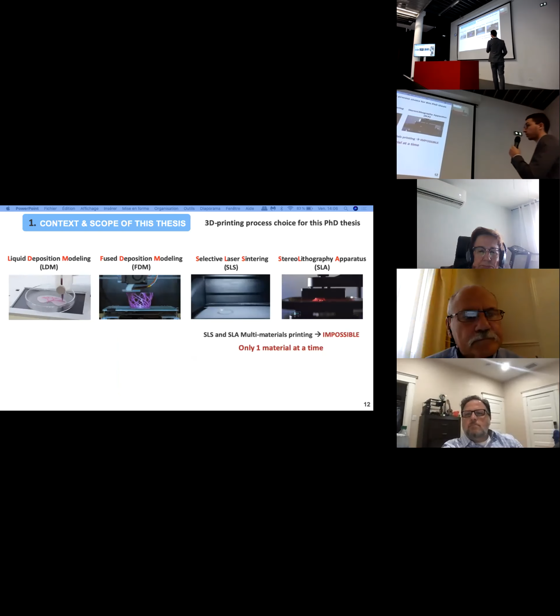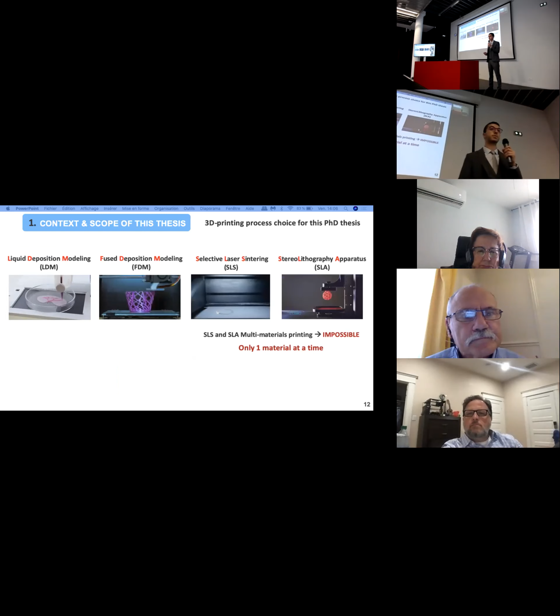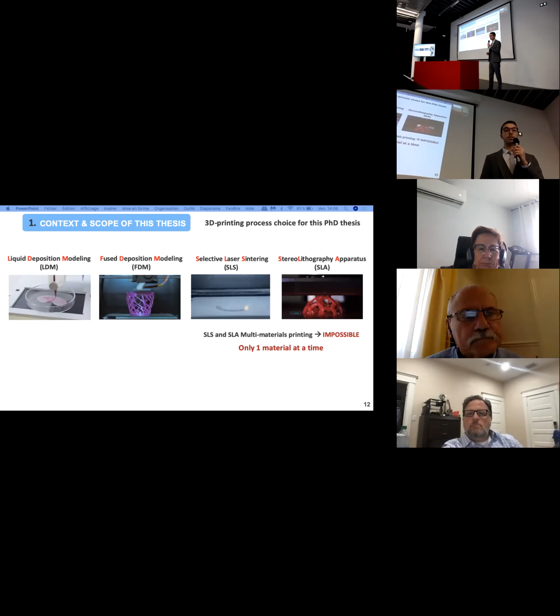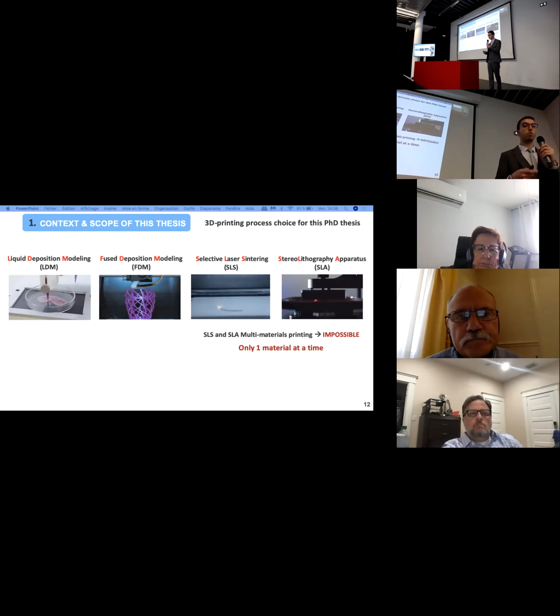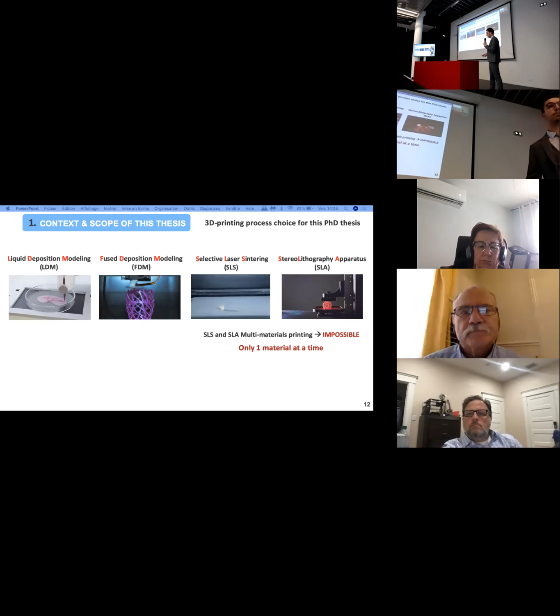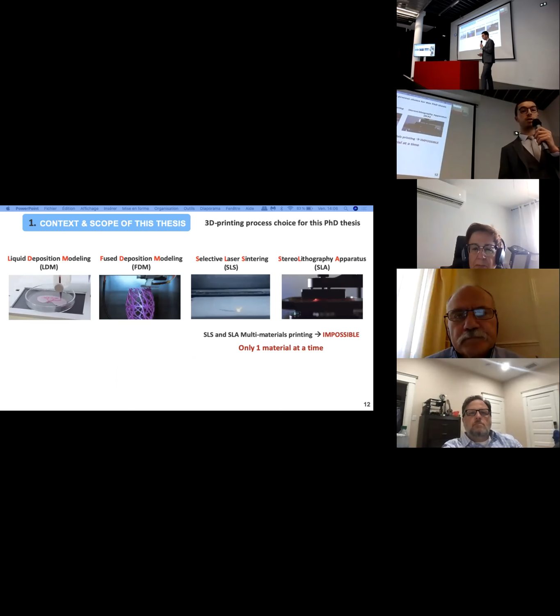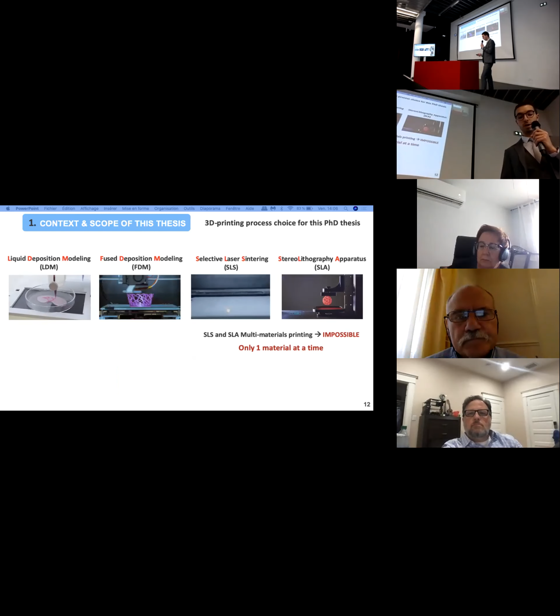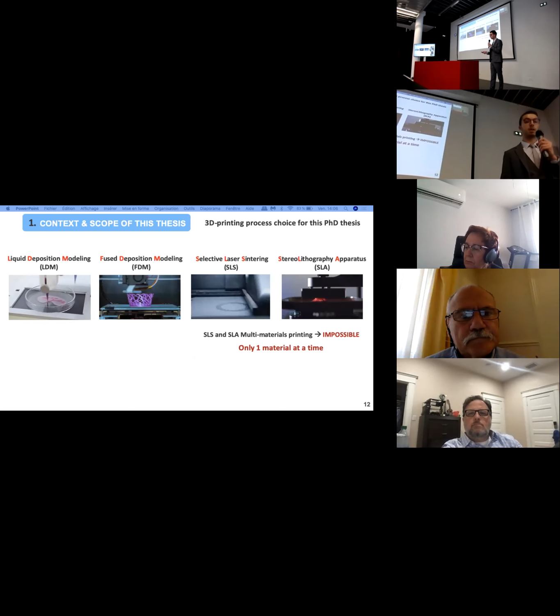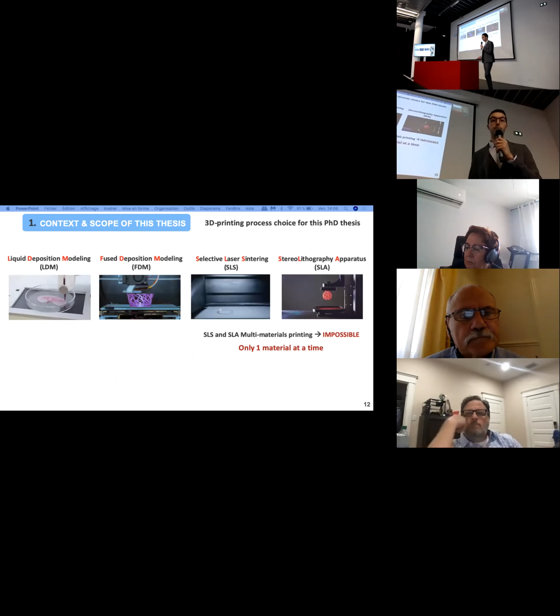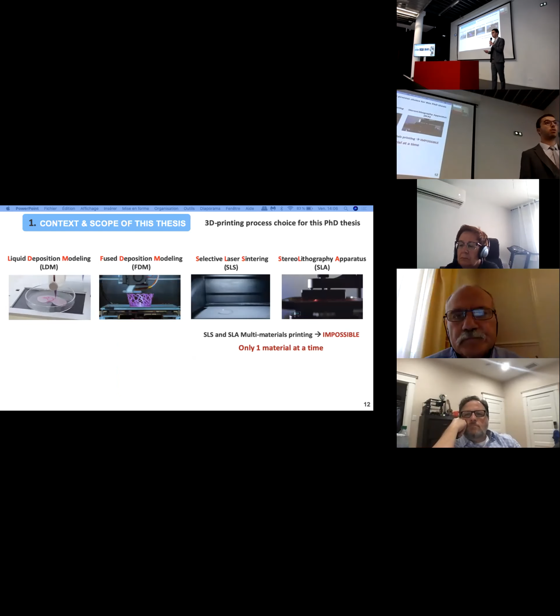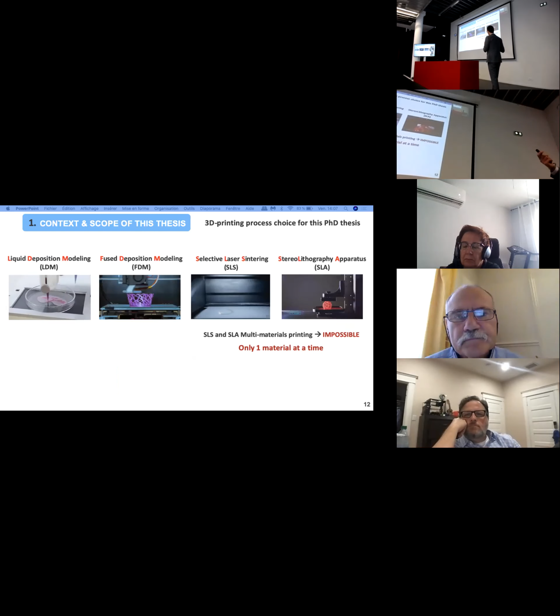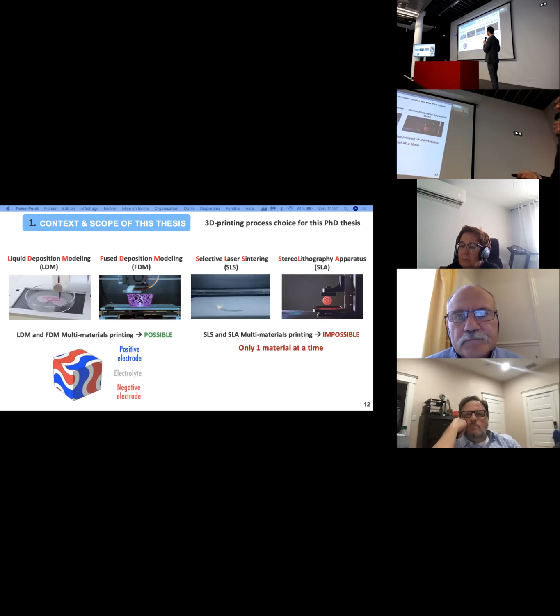So among these four techniques, the first step of this PhD thesis was to make the right choice, right? I mean, we needed to choose among these four processes which process we were going to use to print lithium-ion batteries. And so here, right from the beginning, we decided to exclude from this thesis the selective laser sintering and the stereolithography apparatus, as with both techniques, unfortunately, you cannot print multi-material objects, meaning that you can only print one material at a time. So with both techniques, you cannot imagine printing such a gyroid architecture for the lithium-ion battery.